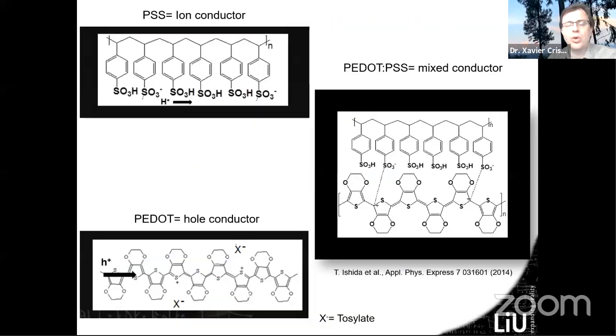So I'm going to show three kinds of polymers just to illustrate. This one on the top left is a polystyrene sulfonate. You see that the polymer chain, the skeleton of the polymer chain, is only composed of single bonds. So this one is not conducting electrons, but they have sulfonate groups here, and they promote proton conductivity. So this one is a polymer that conducts protons, the ions.